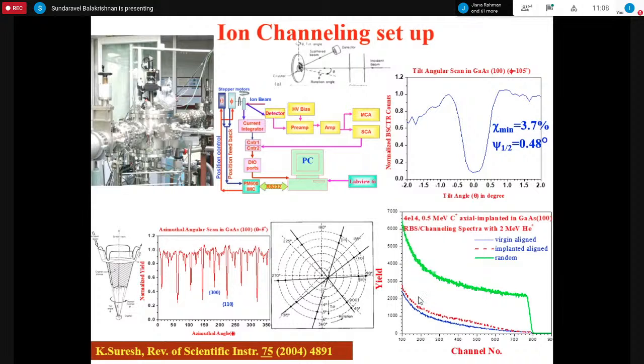And under aligned condition, if we take normal Rutherford backscattering, you see here this blue color curve, where there is much reduction. Here our chi minimum value is something like 3%, and in case in the crystal you do some implantation, due to the presence of defects there will be dechanneling, and from this dechanneled spectra, we'll be able to get the defect density as a function of depth. That I'll be coming to later. And about this axis, if you tilt plus minus 2 degrees, then you'll get this sort of curve, and the width of the curve gives the psi half values.